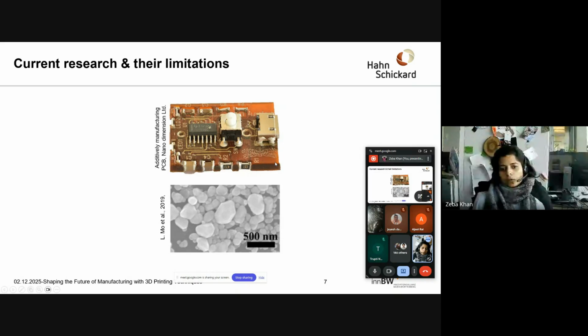This particular printed circuit board was printed with the help of dielectric ink and conductive ink. So the dielectric is the yellow or the orange ink, and the conductive is the silver ink that you see here. They have also showcased how neatly they can assemble some capacitors, resistors, some ICs, etc. Another example here for the current research is the main component of this printed circuit board, which is the conductive ink, which in real form is something like this. So it's a nanoparticle-based solution, in which you remove the solvent and you're left with the nanoparticles, and upon pressure or heat, this can come together and create conductive tracks.